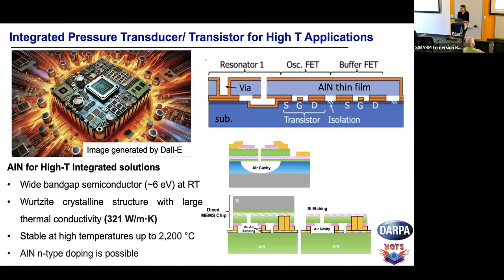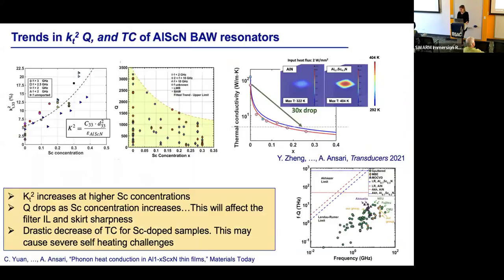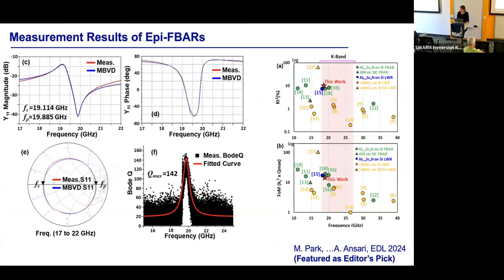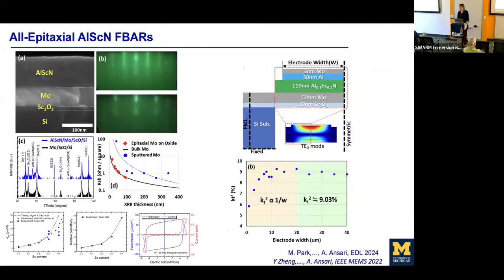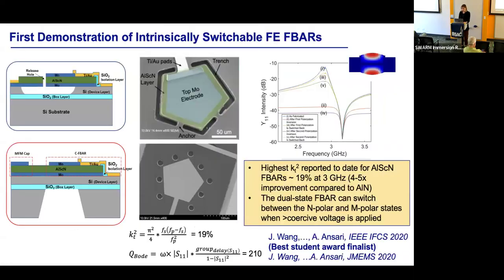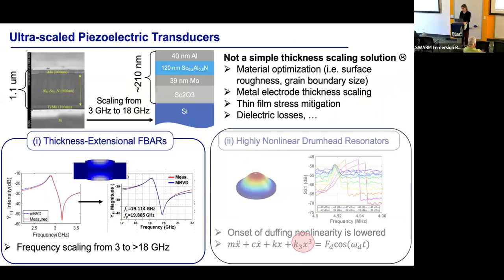Okay. So Will? For the RF resonator project with the aluminum nitride, as you mentioned, there's a trend that even though you get better coupling, the Q factor decreases. Are these two parameters just contradicting each other, because you have more coupling with lower Q? That's a great question also. Generally Q times KT square is a figure of merit, and even within the same material system, usually if one goes up, the other one compensates.